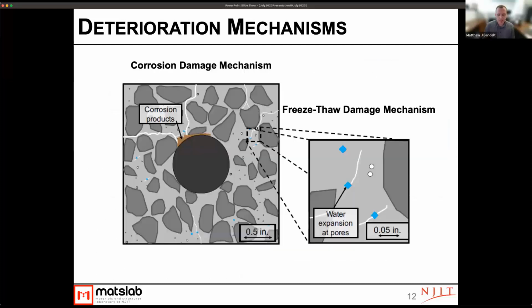In one sense, if you were to think about the different types of deterioration that we see in concrete structures, a lot of them are due to these expansive stresses that build up across different scales. So if you get corrosion products that form around the surface of a piece of reinforcing, those corrosion products, because they have a larger volume than the surrounding initial material, cause these expansive stresses to occur. And a similar phenomenon happens with freeze thaw as well, where you get water expansion within pores and causes cracking just at a different scale.